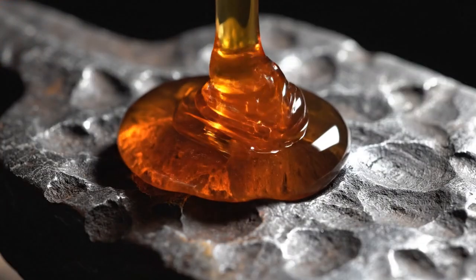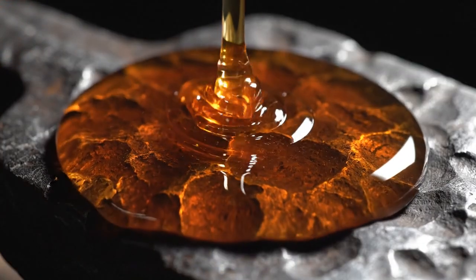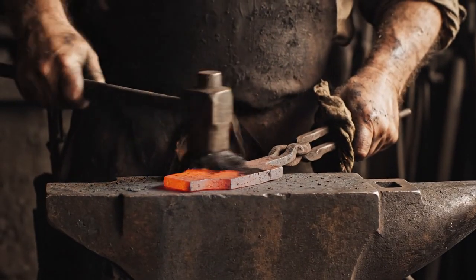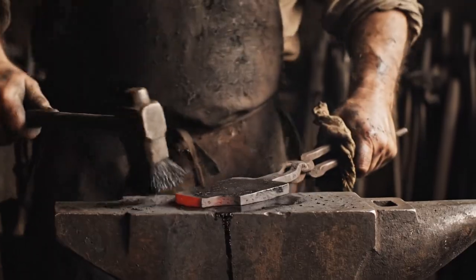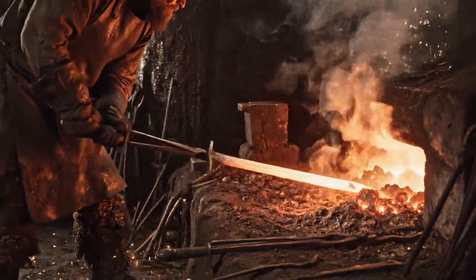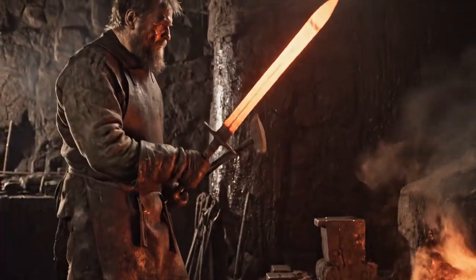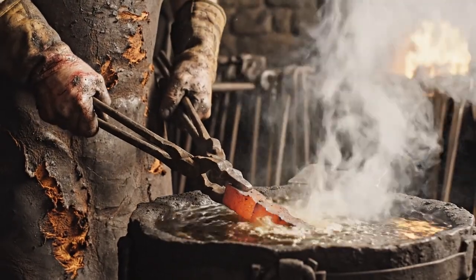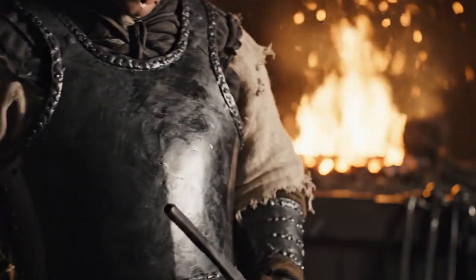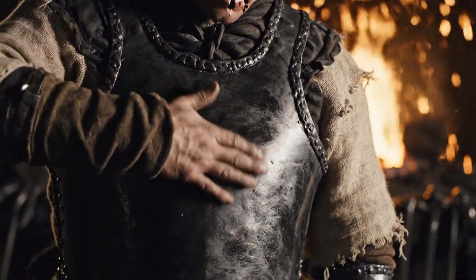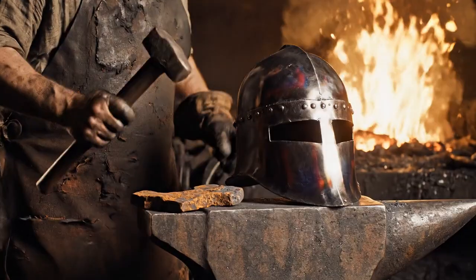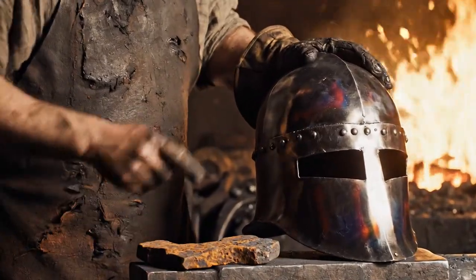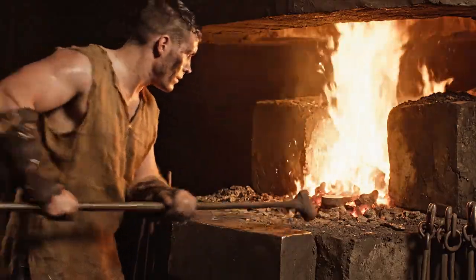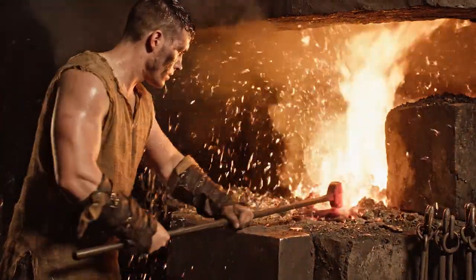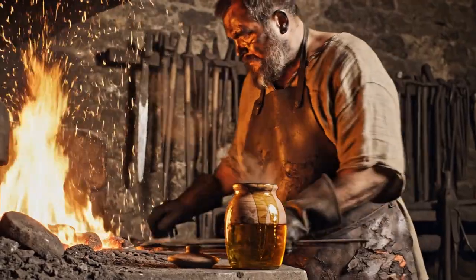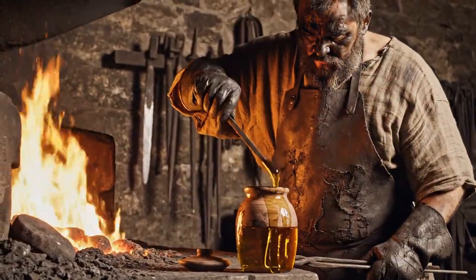This is not a metaphor or a pedagogical simplification. Linseed oil becomes a natural plastic, not the petroleum-derived kind, but a durable, cross-linked polymer that bonds directly to any surface onto which it was applied. And when that surface is hot iron, the resulting bond is permanent. Medieval blacksmiths discovered that applying linseed oil to iron while it was still warm from the forge, not glowing hot, but hot enough for the oil to begin releasing a light smoke, around 200 degrees Celsius, 392 degrees Fahrenheit, produced a dark, resistant finish that prevented moisture and corrosion much more effectively than oil alone applied cold.